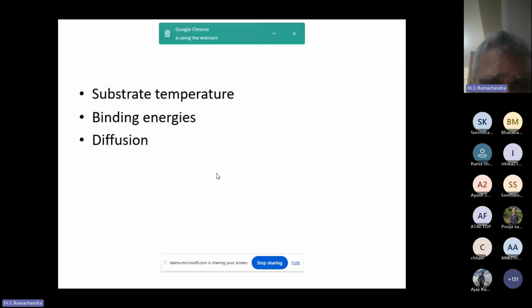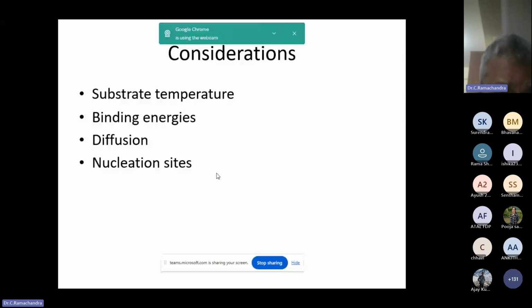There are various parameters which affect the performance and quality of the film. That includes substrate temperature, the binding energy, and how well the molecules diffuse on the surface. And nucleation sites on the substrate. The more nucleation sites, the better for a uniform film. And adhesion: after depositing, how strongly it is adhered. We deposit the films, and if adhesion is poor, it will come off in the next process, so it is of no use. Then for some applications, we need a crystalline structure. So how do we get the crystalline structure? These are the challenges we need to address.